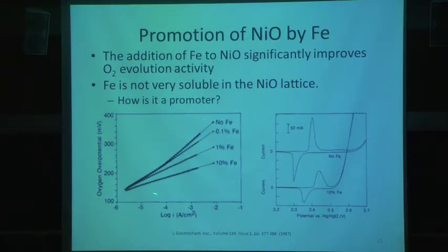So there are two different ways of looking at it. I like this way the best. As you sweep here, this is a nickel 2+ to 3+ oxidation, and then over here you get the oxygen evolution current coming up. If you add a little bit of iron to it, you can see at this potential you get much higher activity. That means you're getting a lot more oxygen coming off this 10% doped iron sample.